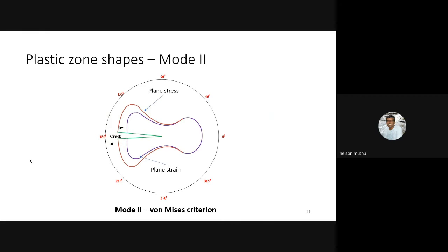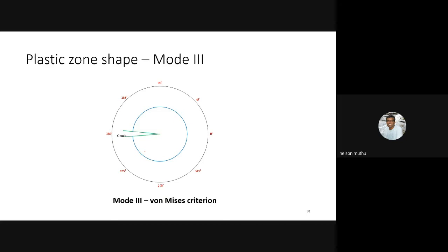Similarly, we can also plot for mode 2. See here in mode 2, we have plane strain. Again, we need to establish the principal stresses. From the principal stresses, you need to make use of the von Mises criterion in this case. So you see the plane strain plastic zone shape is relatively smaller than the plastic zone shape for plane stress. In the case of mode 3, it is one circle. That is by virtue of how we get the stress field solution ahead of the crack tip due to a mode 3 crack. You can see that it is a circle. The von Mises criterion will give you a circle. So that will be the shape of the plastic zone.